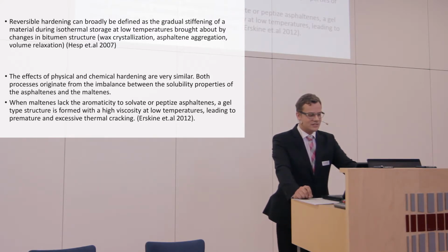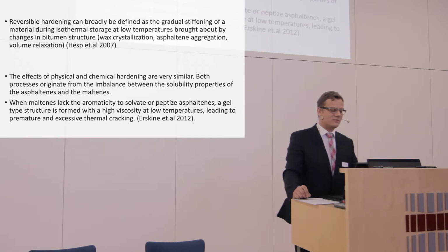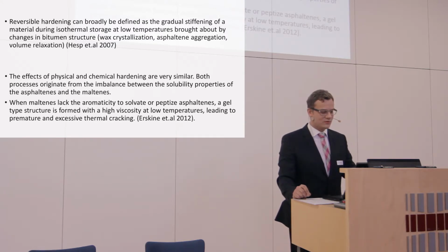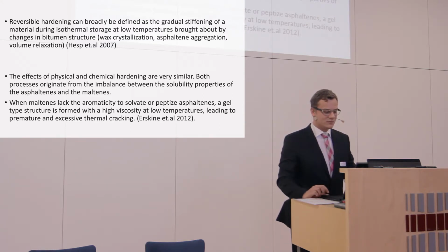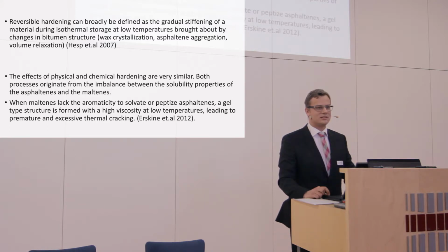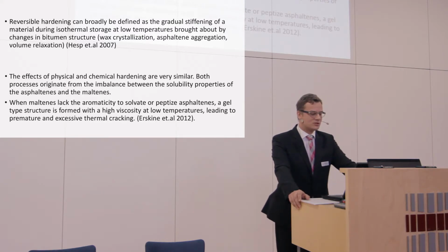The effects of physical and chemical hardening are very similar. Both processes originate from the imbalance between the solubility properties of the asphaltenes and the maltenes. That means when maltenes lack their aromaticity to solvate or peptize asphaltenes, a gel-type structure is formed with a high viscosity at low temperatures, leading to premature and excessive thermal cracking.